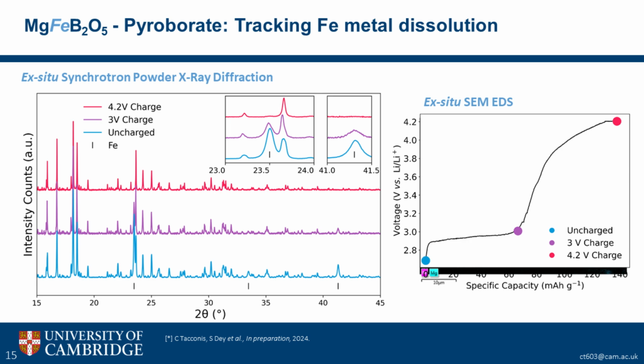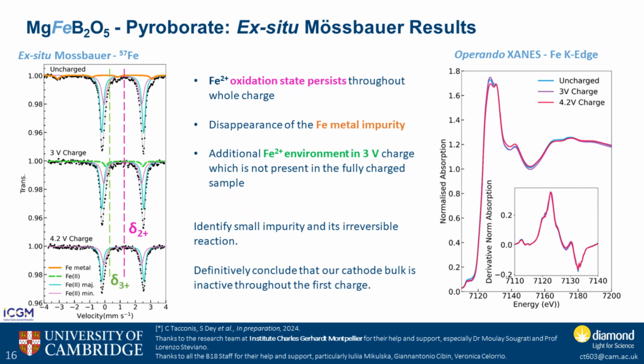And what we did see, however, was that the peaks here, which are zoomed in on the insets, that we associated to our iron metal impurity, if you remember, it was this 4 weight percent that was coming out of our synthesis, were disappearing throughout the first charge. We also ran some SEM EDS, and it didn't show significant demagnesiation from the surface. I'm not going to show the results here, but what I wanted to show in the pristine material is that you can clearly see the morphology of these iron metal impurities segregated from the main phase of our cathode material. So this is the Mossbauer that we collected.